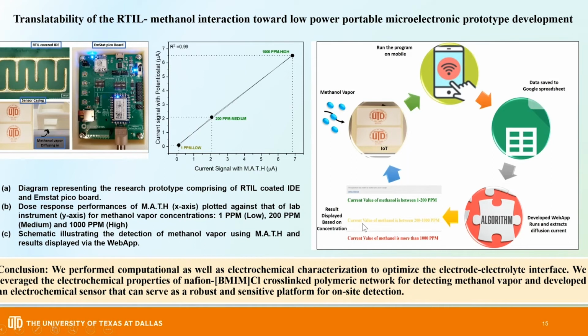The current value of methanol between 200 and 1000 is the medium range, and a value greater than 1000 is the highest range. That is the alarming range, if you can say. So we performed computational as well as electrochemical characterization to optimize, and we reported the electrochemical properties of a Nafion RTIL cross-linked polymeric network for detecting methanol, such that the developed electrochemical sensor platform can serve as a robust and sensitive